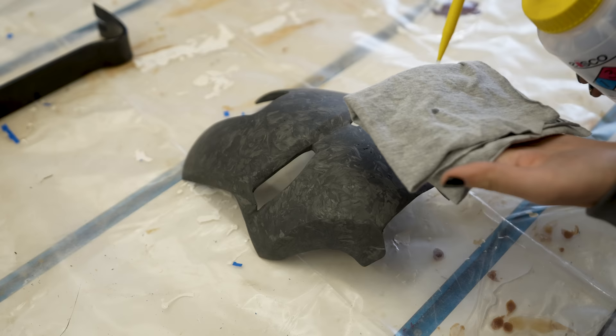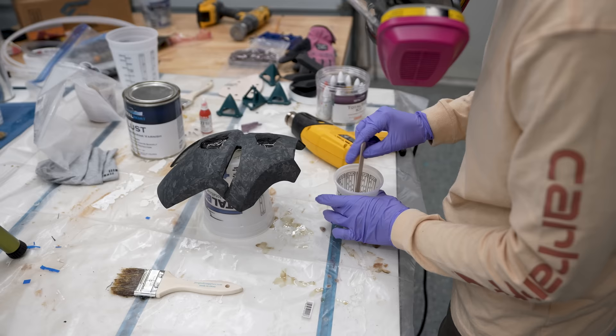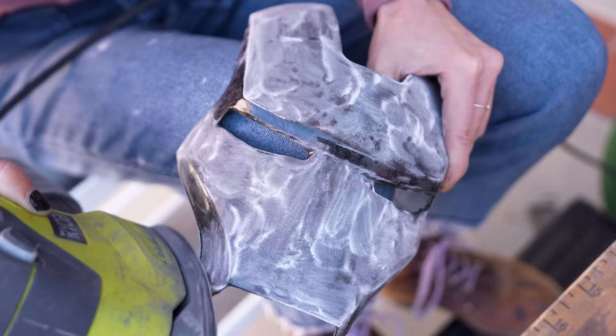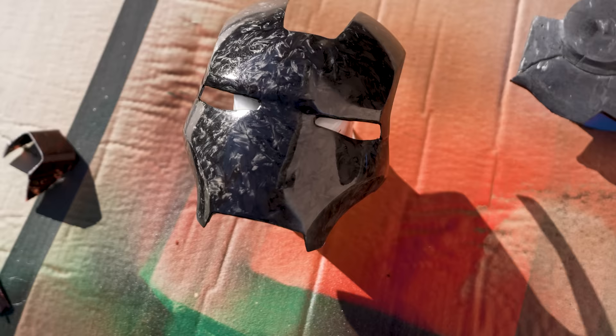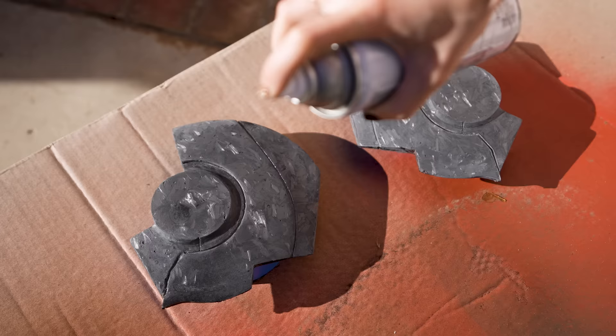Once I had the mask smooth and looking a little bit less like Iron Man is having an acne problem, there were a few air bubbles and gaps and voids in the surface of the carbon. I'm not sure if that's avoidable if you don't vacuum infuse it — if anyone has suggestions, please let me know in the comments. I solved this by painting a thin flood coat of epoxy over that to get into those bubbles and fill them, giving a nice smooth finish that seals the carbon and really makes it pop. Once that's cured, I could go in and give it that beautiful finish sanding. I went up to 400 grit and after a good wipe down with isopropyl, it was time to start layering coats of spray-on clear coat. That's how I'm going to get my final gloss. Look how pretty it is — it's just so shiny.